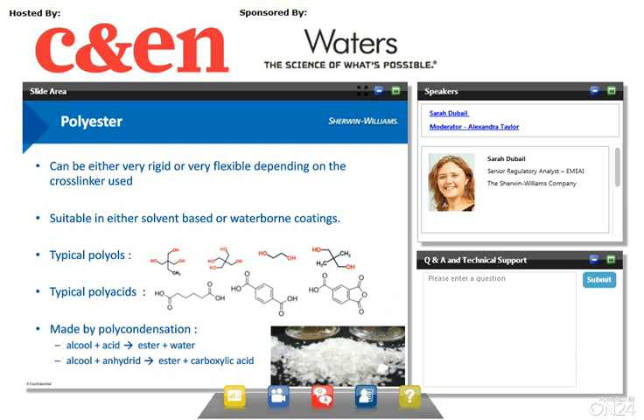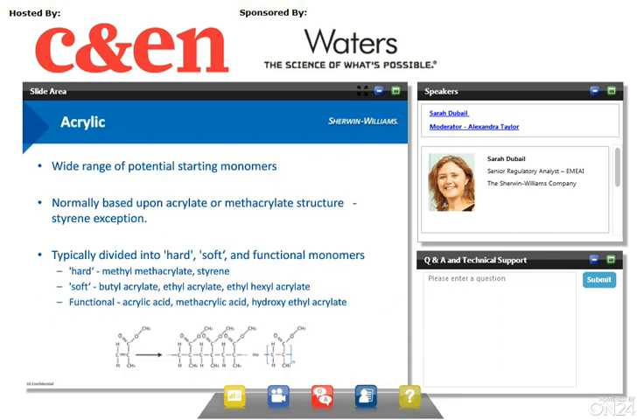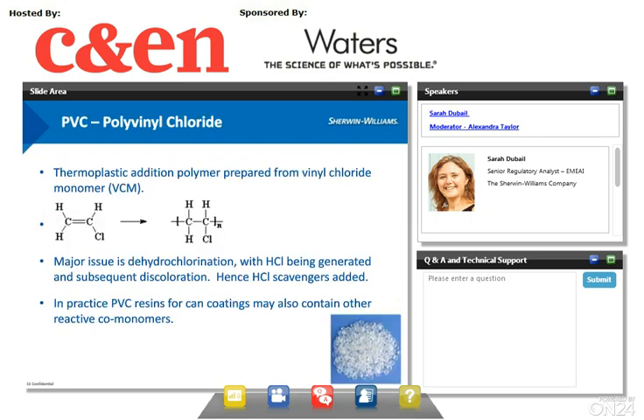Alkyd resins are a subfamily of polyesters, with vegetable oils used instead of the acids. In this case, the molecular weights are lower, with fatty acids from the vegetable oil acting as a chain stopper. Acrylic resins have good appearance properties — they preserve color and gloss. They are made by polyaddition and are often of very high molecular weight. When dispersed into water, they take the name of latex. They are made from a wide range of potential starting monomers, usually based on acrylate or methacrylate structures.